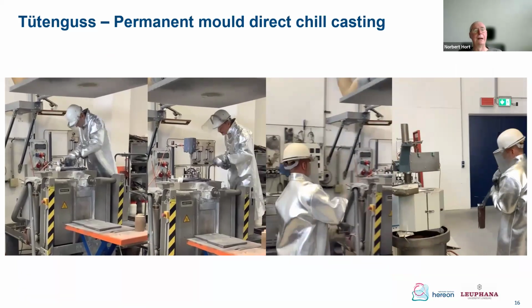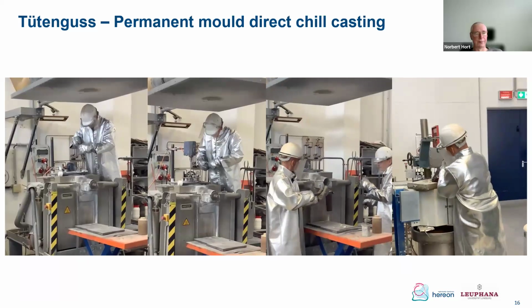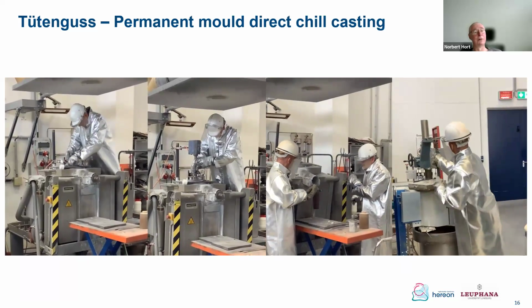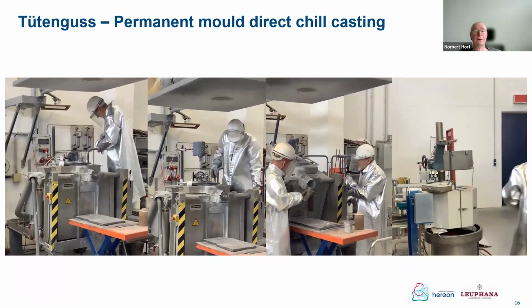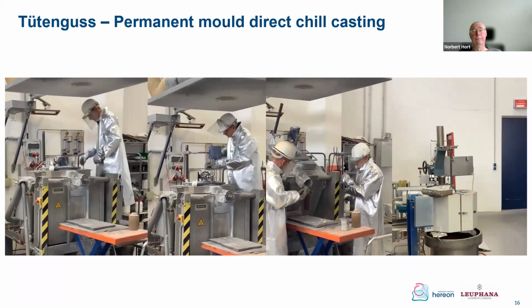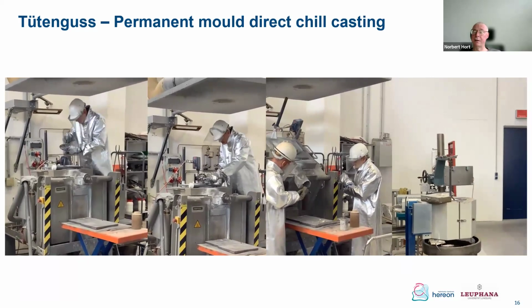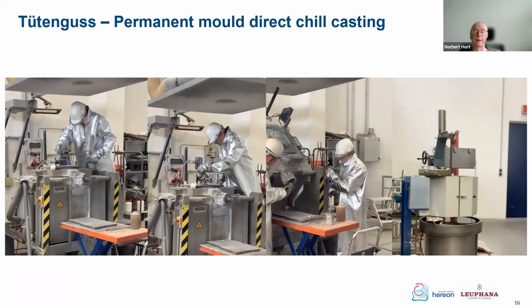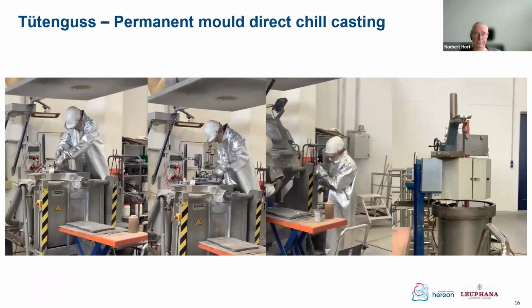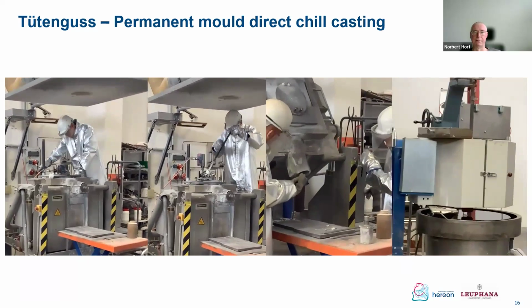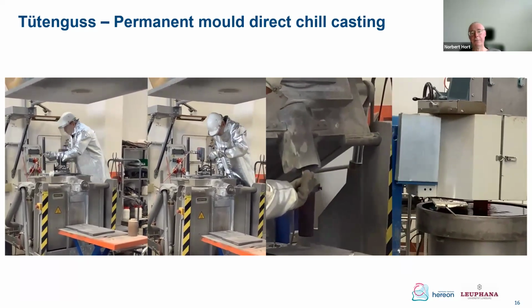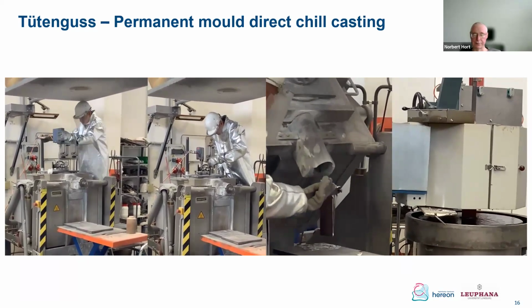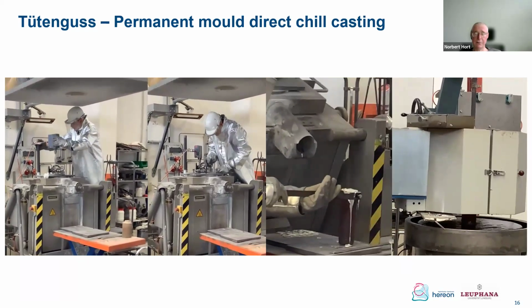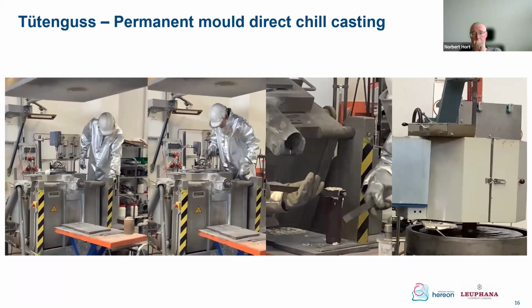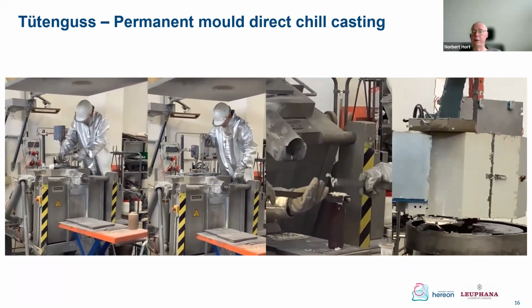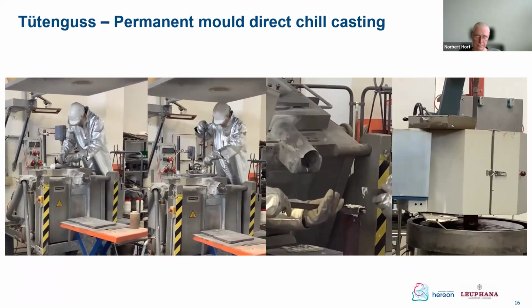And that's our daily work for that. On the left-hand side, you see how my colleague is adding the alloying elements. The left in the middle, he's stirring that, then we are casting that, and the good message, quite often magnesium is told to be highly flammable, but you see, no flames at all. So the cover gas is doing what is necessary. And on the right-hand side, you see the mold is getting dipped into the water bath, cooling down completely.